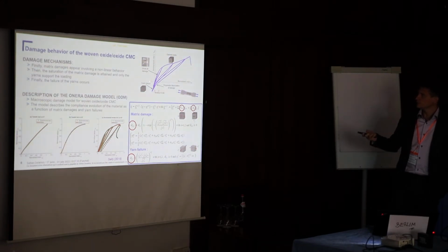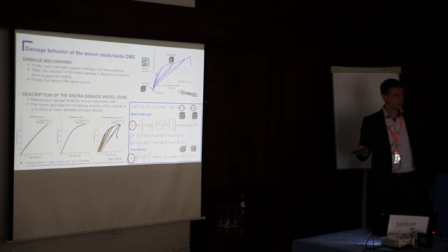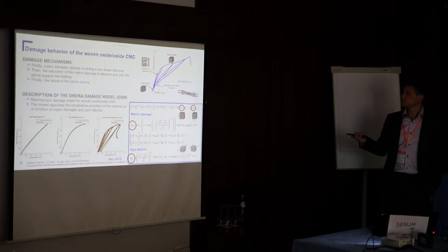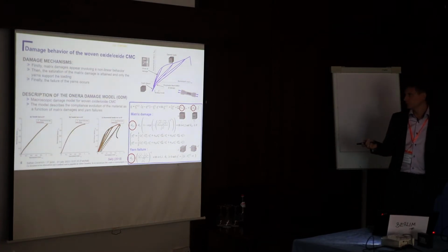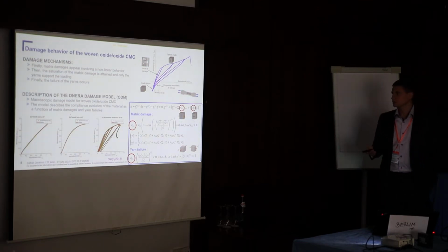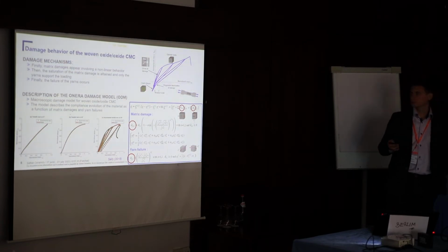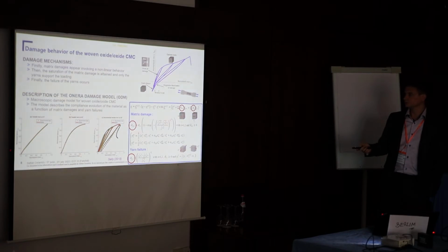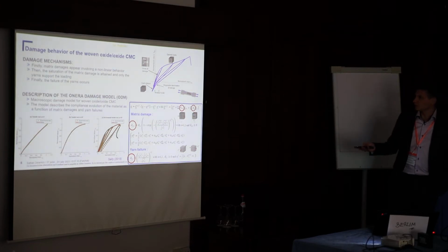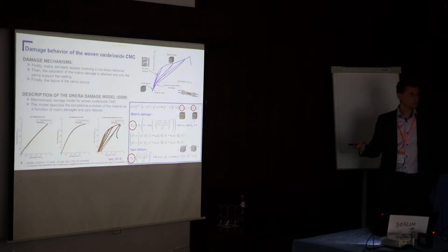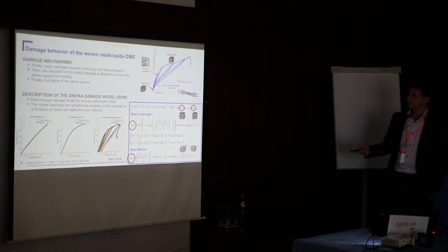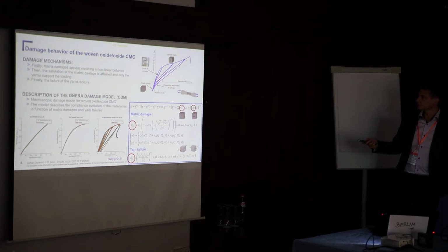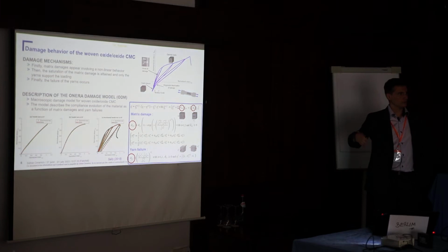In order to model this kind of behavior, we use a macroscopic damage model for woven oxide CMC, which is the Onera damage model developed at Onera in France. This model describes the compliance evolution of the materials as a function of matrix damages and yarn failures. Here we can see an identification of the model using experimental data under tensile test with different orientations of the microstructure of the woven materials. I don't have the time to describe the whole model, but just remember that we have two damage variables per microstructure orientation: DM for the matrix damage and DF for the yarn failure. These two scalars participate in the compliance under strain.